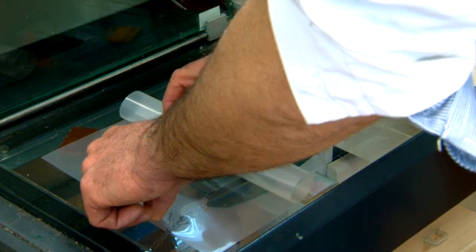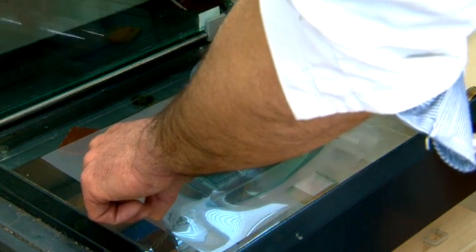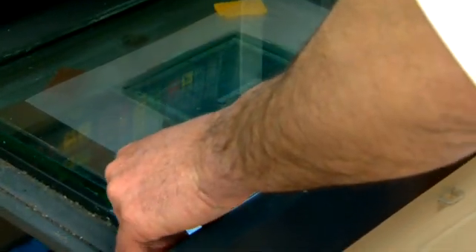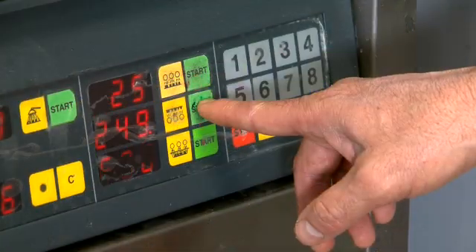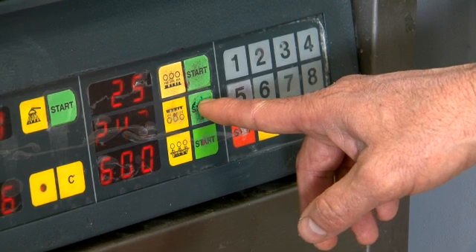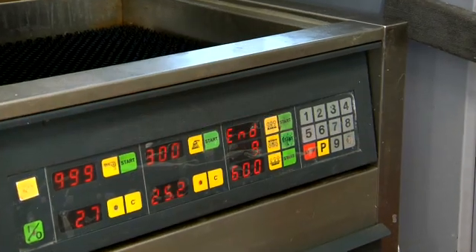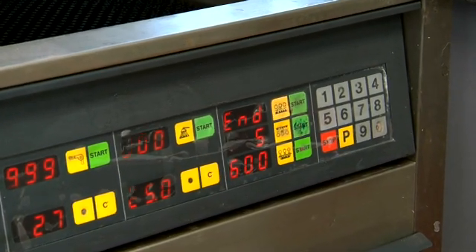We lay the subject film — 20 seconds. We shut the glass, and as a consequence exceeding resin will overflow. We start UV light exposure. Times depend on how powerful and how worn out the lamps are, and on which resin we are using — standard or fast — from 150 to 300 seconds.